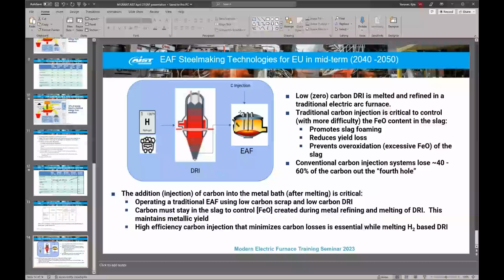making sure you're doing a good job processing the steel at the EAF, doing all the things that you're supposed to do, and removing the other residuals in there, which you can remove, and making a good foamy slag that protects the arc, protects the furnace, keeps heat transferring to the bath, removing nitrogen, all those good things that we're trying to do in the electric arc furnace. So there's a lot of flexibility there. And that's one of, to me, their biggest strengths.